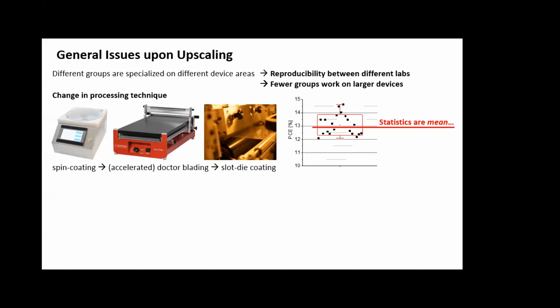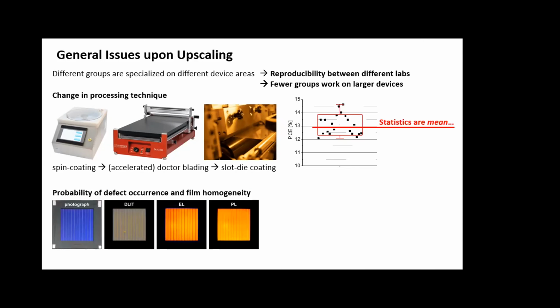Another thing is that statistics are really mean. A person working on square millimeters is happy about this result and can present a champion device with 14.5%, not caring about the mean value, about the statistics of the other devices. The one champion device is the good one, but the poor guy who needs to upscale this to square centimeters is having a really hard time, because there's absolutely no possibility for him to reach 14.5% if only 5% of the area is working with this percentage. So you have to live with the mean value, and this is only the best case actually, because this does not include defects or something like that.